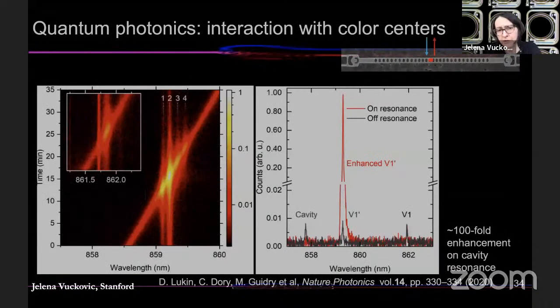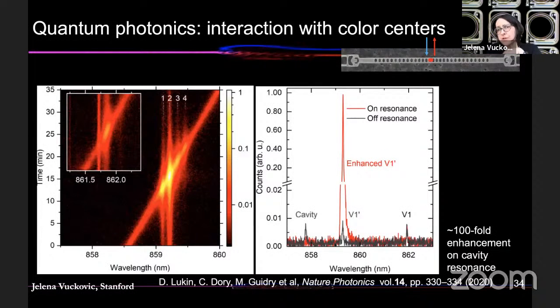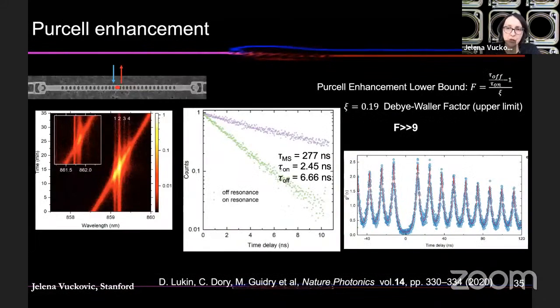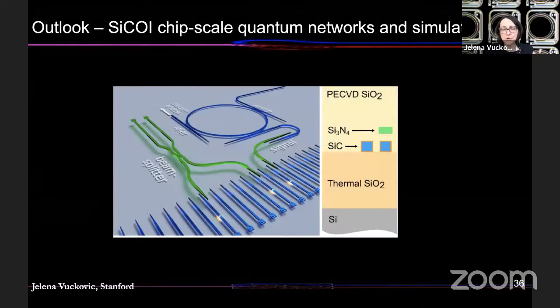And on top of everything, in the process of producing silicon carbide on insulator, we don't really degrade color centers. They have excellent properties. We can couple them to cavities, and we've shown strong enhancement of their emission on cavity resonance by a factor greater than 100, reduction of radiative lifetime, and we've also measured photon statistics. So we're now going in the direction of scaling this, connecting different quantum emitters.